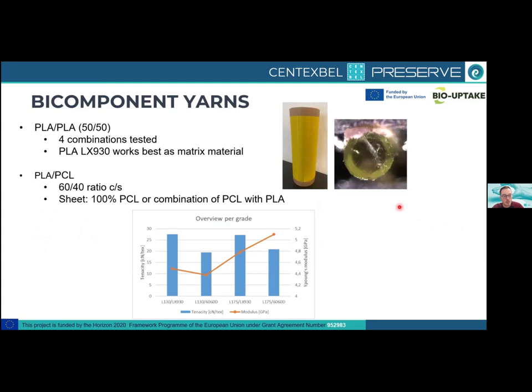And then some technical information on how we can create this. I wanted to show it because the bicomponent is sometimes a little bit difficult to understand, how this is created. You can see here on the picture on the right, we have put a yellow masterbatch in the outside of this material. So you can see it's yellow on the outside of the fiber, and in the middle it is just no color because we did not add color there. And then you can see really that we have on the outside the low melting PLA one. And also with PCL, we have tried different combinations, different types of grades, but also different ratios to see which one has the best strength and performance in making the composites.